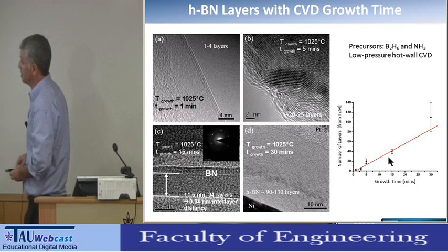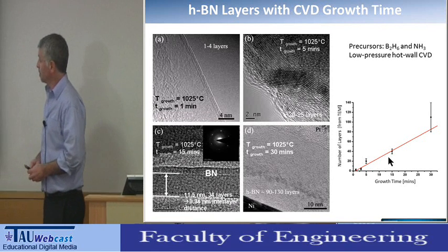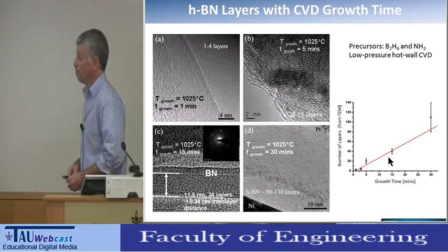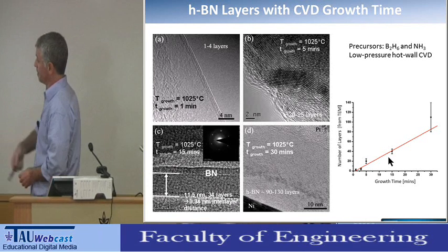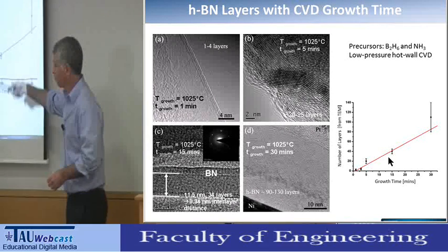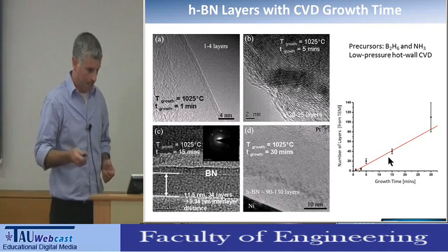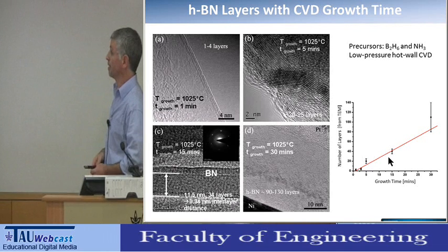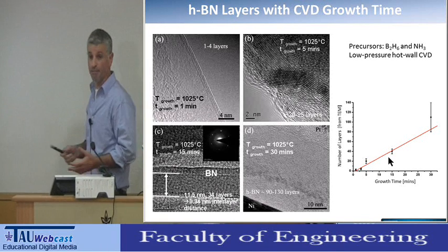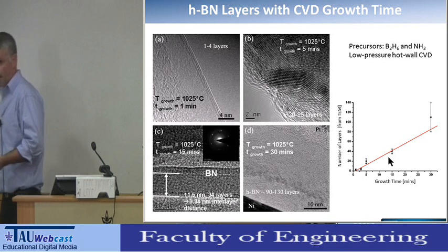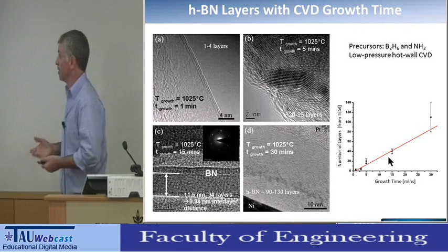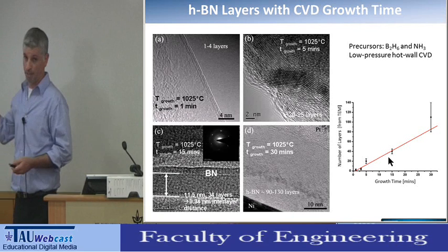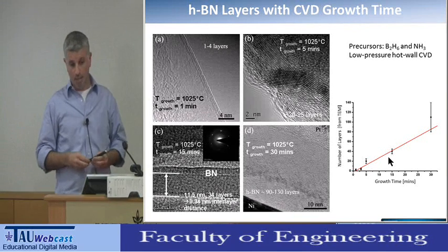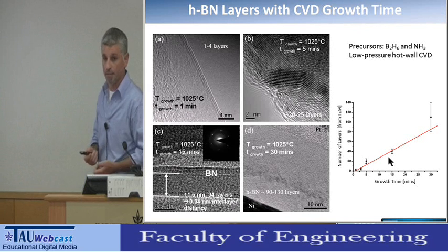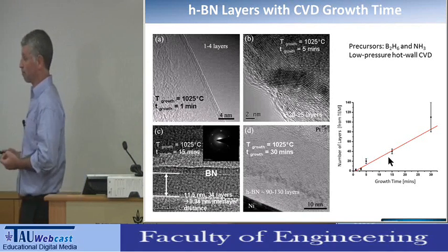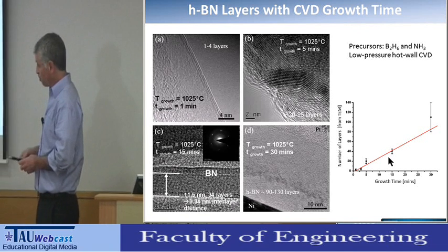But one thing that we notice is that we could achieve a relatively easy control over the thickness just by controlling the reaction time. So you may say that this is trivial. This is trivial maybe for classical thin films, in which if you grow them for longer times, you get thicker films, and that makes sense, but not for layered compounds. In fact, you can't grow graphene on graphite. There is no way that you can grow graphene on graphite. So the question why and how